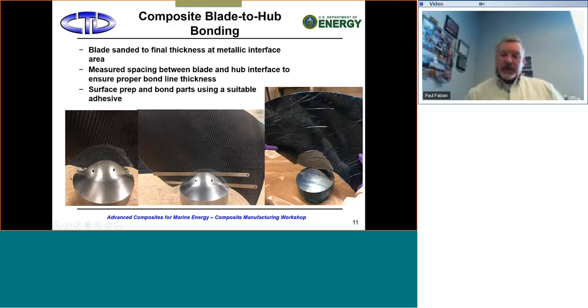And so here you see, we've applied the adhesive. The adhesive was also applied into the metallic, and it's being placed in there. There are some tricks that you use to make sure that you maintain that bond line thickness, but really nothing major. You should notice here that there are 2 holes. We also match drilled the part once it was bonded and put 2 pins through here just as a safety measure, just to make sure that we had sufficient margin and make sure we didn't have anything catastrophic happen once we were actually testing. We did do a lot of FEA and analysis on the bond line, to make sure it could withstand the stresses that we were going to place on it.